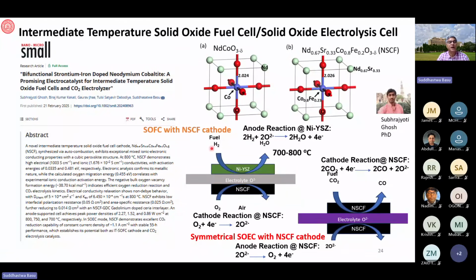So we can use it as a solid oxide fuel cell or a solid oxide cell. In a solid oxide fuel cell, you use hydrogen as a fuel. You use nickel-YSZ as the anode, and NSCF, the one that I told you about, as the cathode, and you have an oxide ion conducting electrolyte, which could be YSZ or GDC. You can use a similar cell, NSCF and NSCF symmetric cell with the electrolyte, for electrolysis, as a solid oxide cell. So CO2 is electrolyzed to CO, and the oxide ion gives oxygen out in this case.